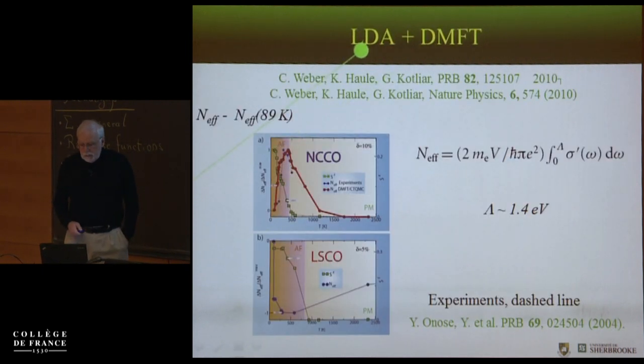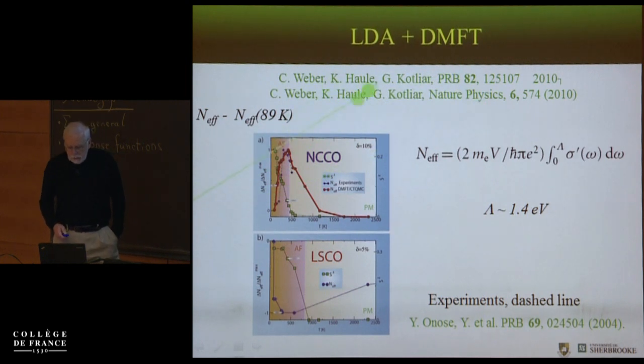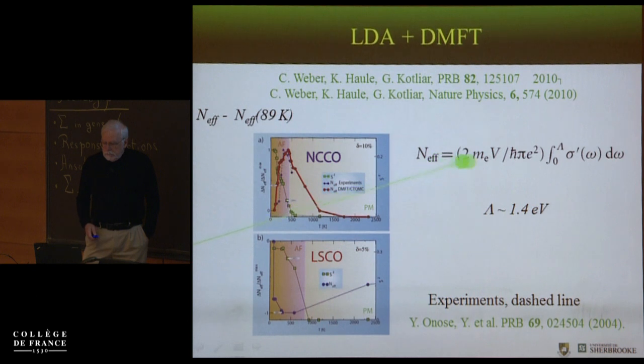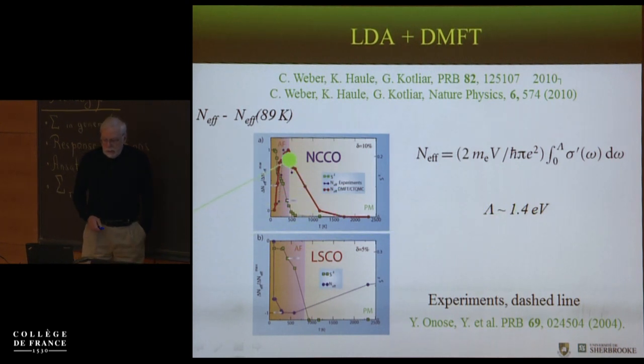The other one is these calculations of LDA plus DMFT from the Rutgers group, and they evaluated an effective kinetic energy by using the f-sum rule, integrated up to some cutoff. The argument is not so simple, and I'm not sure I understand all the details, but the statement is that if you are in this Slater or weakly correlated limit, as you enter the antiferromagnet, this kinetic energy should go down. Whereas if you're in a Mott system, like in hole-doped LSCO, it's the other way around. So this is this effective sum rule as a function of temperature for 10% doping, and you see that the trend is different here. When you enter the antiferromagnet, it's going up.